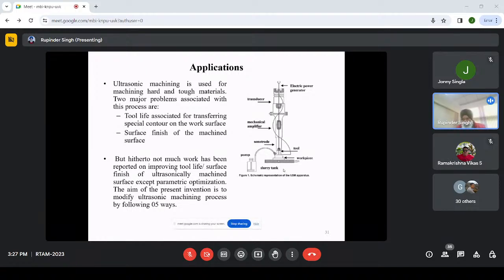Now I have personally worked on this machine. This type of transducer for a machine like the Sonic Mill, which is a US-based machine, costs something around $80, whereas my transducer is available for as low as 20 rupees, because I just have to print some successive layers and I can control the compaction and expansion, and basically control the amplitude of the vibration. So that is one beauty, and we can make our own setup with this and control some of the mechanical motion over here.